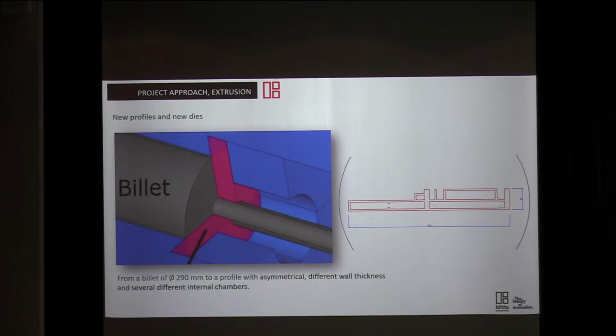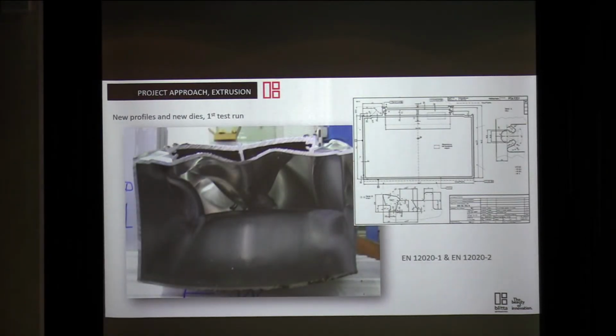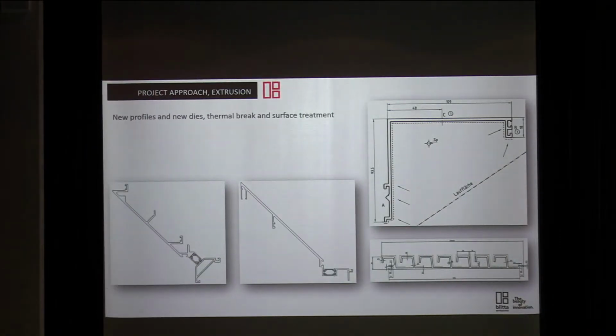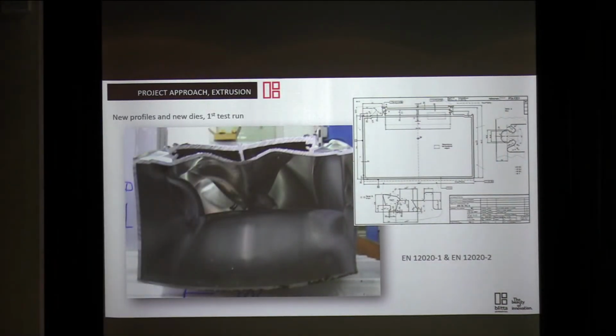Here is a very big wall thickness, here a small wall thickness. Here a little bit of parts of it. Here large and broad. So it was a very demanding profile to get out. This is the same, for a very big building in Rotterdam. You see here the theoretical part in the picture. But when it comes out of the die the first time, it looks like this. So it's a very complex profile.